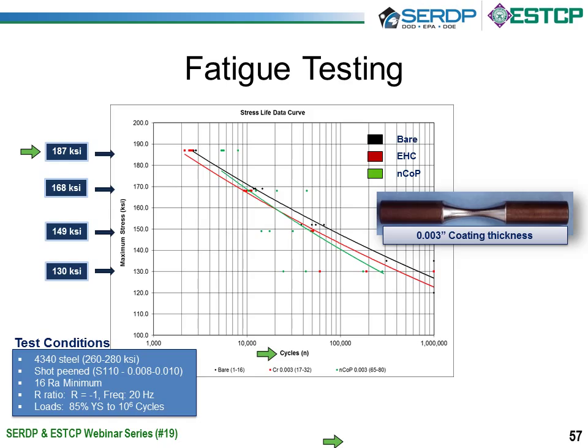We duplicated this test for greater thicknesses, 10 and 20 thousandths, as well as utilizing nickel underplates. So there's a great deal of fatigue data, and that data has a lot of statistical analysis in our test report that was issued. At the moment, we are consulting with our structural engineers to assess this data and determine whether or not additional fatigue testing is required at either different load levels, different frequencies, or different ratios in terms of how much stress is actually relieved during the fatigue test.